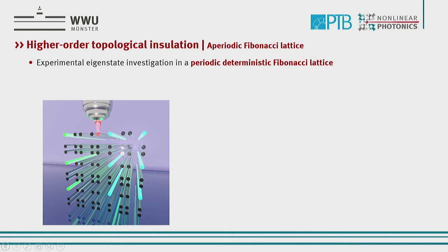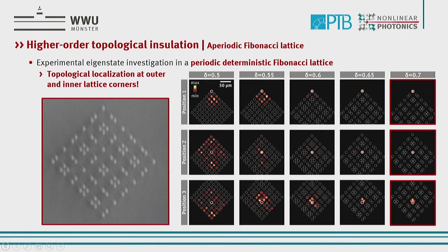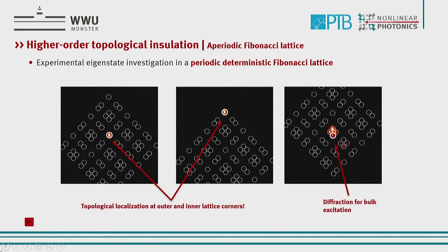And this is now the striking thing, that if we write such a structure and we look at light propagation, we see that at the first glance, with light propagation at position one at the edge, the propagation goes onto the edge. Now, if we are at an area in the middle, we also see that for this area in the middle, we have an inner topological protection. But if you go to other points in the middle, we don't have inner topological protection. And this is due to this sort of structure here, because we have different distances between the different couplings within the propagation of these waves in the Brillouin zone. So what we see is, on the one hand, we have topological insulation at the center or at the edges, but we also have diffraction in the bulk. And that is a quite striking feature that we have here.